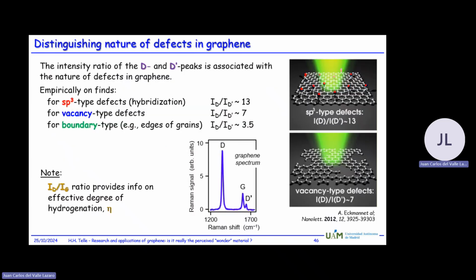Okay. Now, the final bit we have actually shown here, and not only shown by us, but other people, and there are lots of theoretical investigations of this, is that basically you have two types of defects. One is that you have actually atoms or molecules absorbed onto your surface. But the other defect, which disrupts the flow of current, is actually mechanical defects, where your graphene layer is destroyed. There are holes in it. And also, therefore, there is less current flowing through it. So how do you distinguish between these two? Because basically, these defects will result in similar signals in your spectrum.